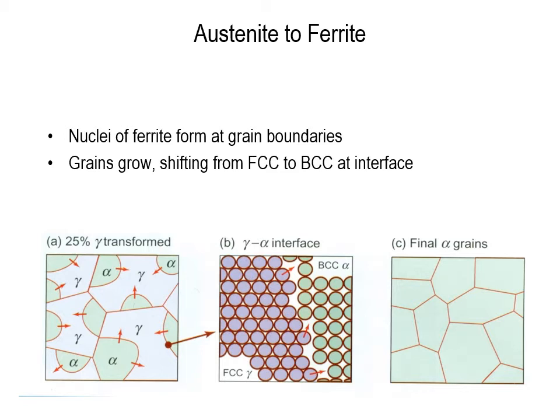So we have a couple of images in this slide here. Now we can see that the nuclei of the ferrite form at the grain boundaries. So grains grow, shifting from a face-centered cubic to a body-centered cubic at this interface. This is going from austenite to ferrite.